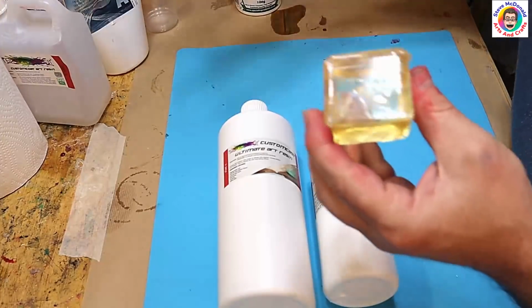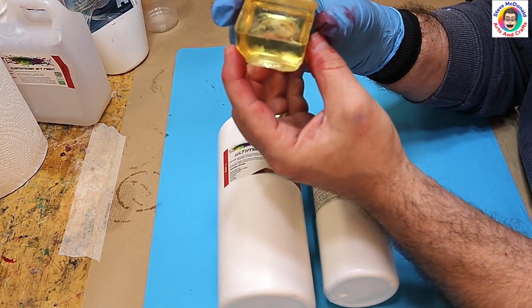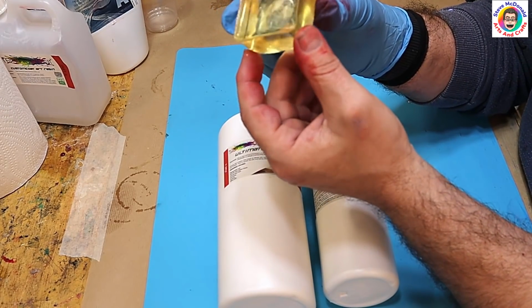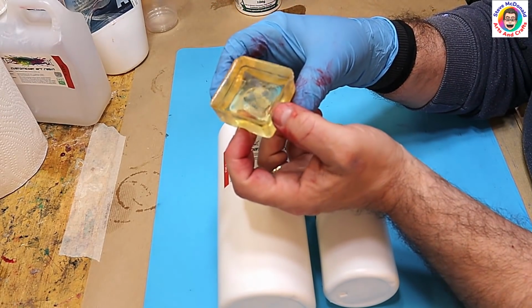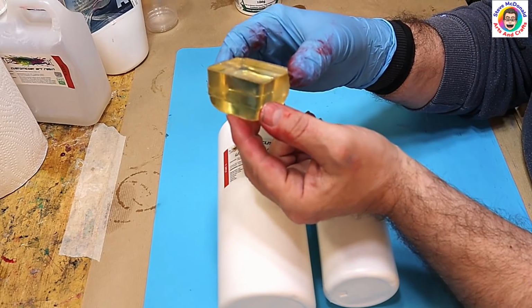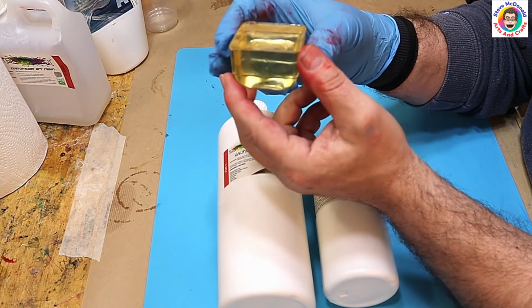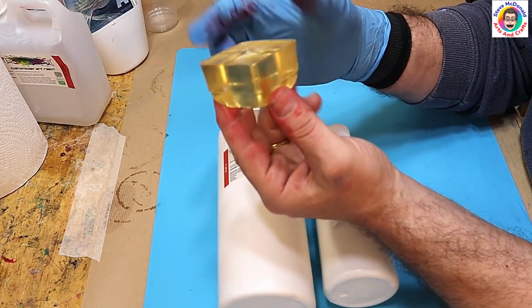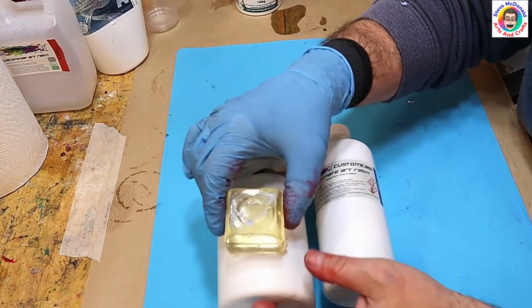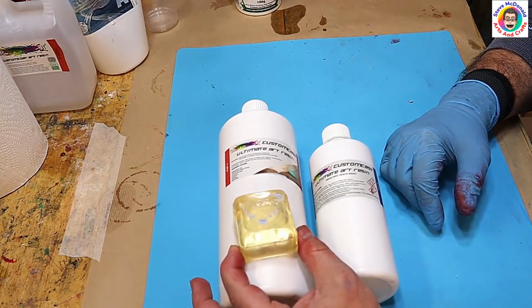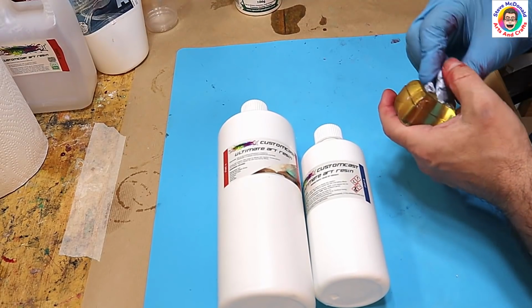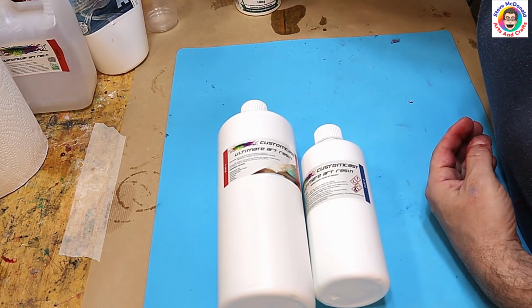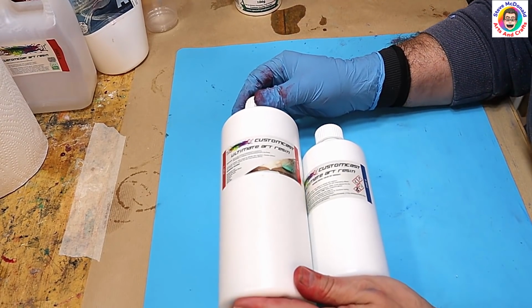This is what I keep my blue tack on, so that's blue tack on the bottom of that, and that was too deep for an art resin. I had it left over in a pot, forgot about it, and it cured up. And what happened is, as you can see, let's put it against the white of that bottle, it's really quite yellow. So that won't help. That wasn't Resin Colour's resin, that was before I got hold of Resin Colour.